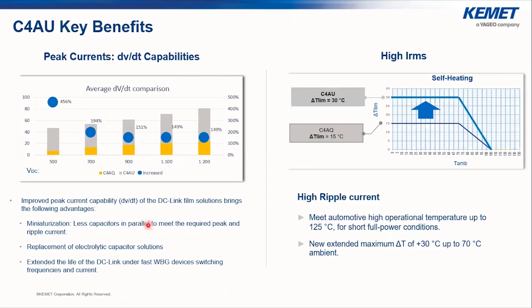So these advances bring some advantages of C4AU. The miniaturization allows fewer capacitors in parallel to meet the required peak and ripple current, and the replacement of an electrolytic capacitor solution. Basically, the miniaturization and the high peak current capability allow extended life of the DC-link and the fast wide bandgap devices, switching frequencies, and also current. As you can see, this series also has high ripple current capability with self-heating up to delta T of 30 degrees until 70 degrees Celsius. That is 15 degrees higher than the C4AQ.